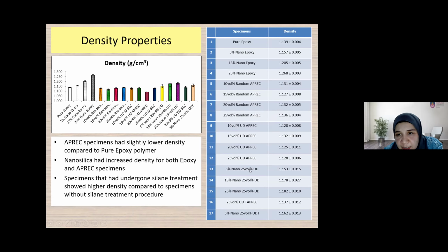And if we put 5% of nanosilica in 25 volume% Arenga Pinnata fiber, the density is about 1.15 gram per centimeter cube. So as we increase the nanosilica, of course the density increases. With the treatment, TAPREC means surface treated Arenga Pinnata fiber. We surface treated 25 volume% Arenga Pinnata fiber, and the density, of course, is almost similar to the untreated fiber.